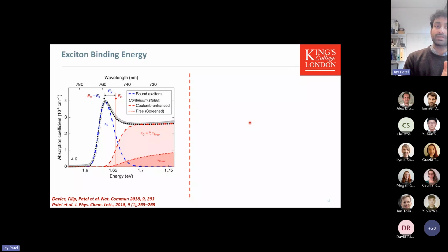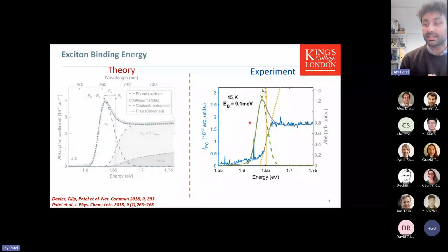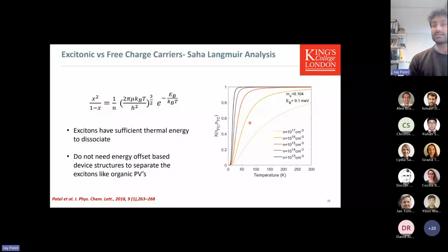In the case of perovskites, we actually calculated the binding energy to be much, much lower than room temperature. Therefore, if you do the calculations, you find that when you illuminate this perovskite material at room temperature using the same intensity as the sun, all of the excited electrons are free to move wherever they want, rather than be tightly bound to the space that they've left behind. So this all bodes really well in terms of the intrinsic physics properties of these materials.